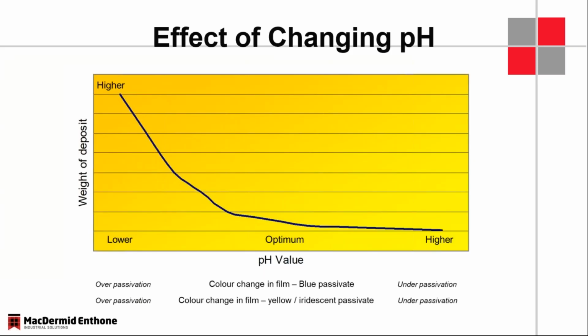So as I was talking about the pH, on the left-hand side you see the weight of the deposit. You could also call that the film thickness. So the lower the pH, the more zinc you're going to be dissolving, the faster you're going to be forming that film. Then you're going to reach your optimum level. And that's where you're going to get a good color change depending on what Passivate you're using. And then if the pH gets too high, you don't remove enough zinc. And actually, if it got too high after that, you wouldn't even be able to precipitate the chrome out of solution.